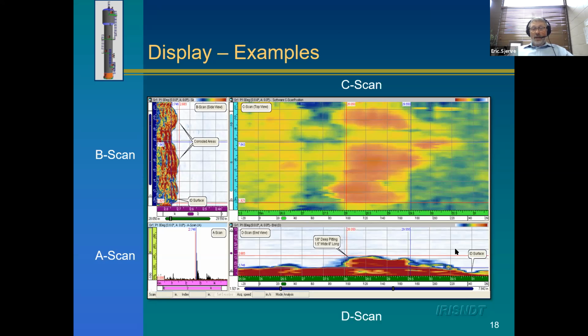And the A scan is in the bottom left. So that's just the sound pressure on the y-axis versus time or depth on the x-axis. The C scan on the upper right is where we just use color to denote thickness. So blue is normal thickness, yellow is some corrosion, red is a lot of wall loss, a lot of corrosion.